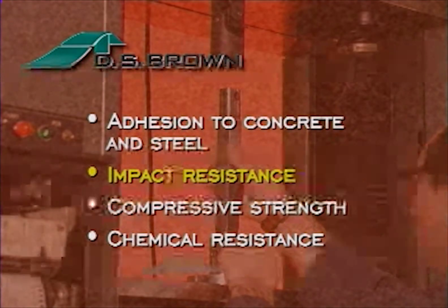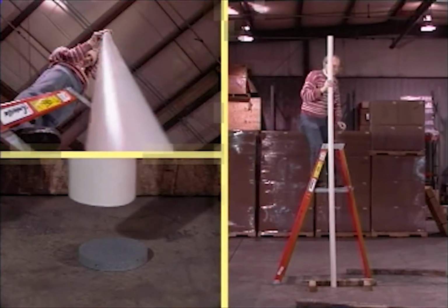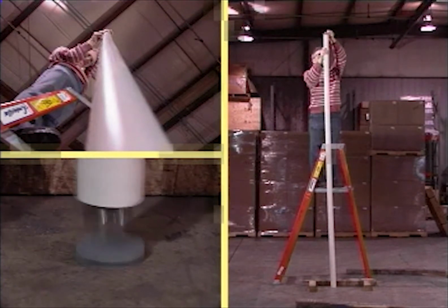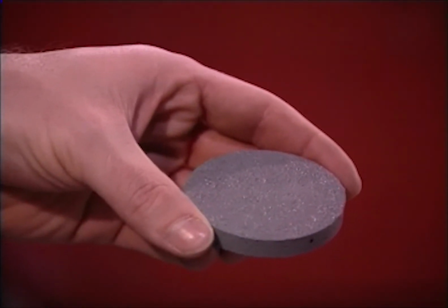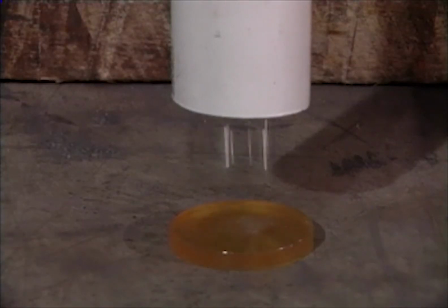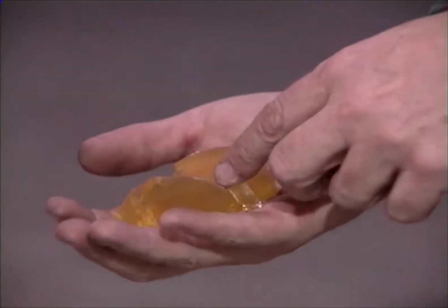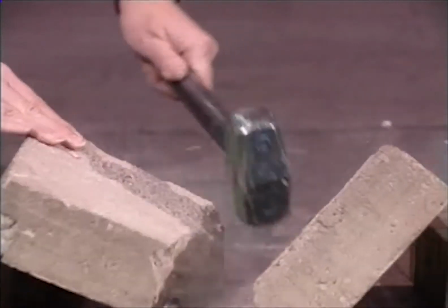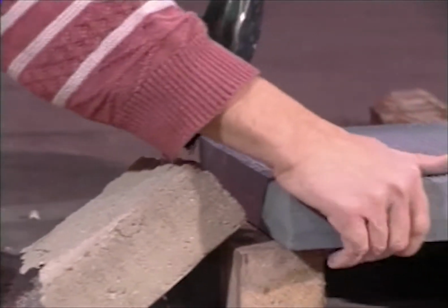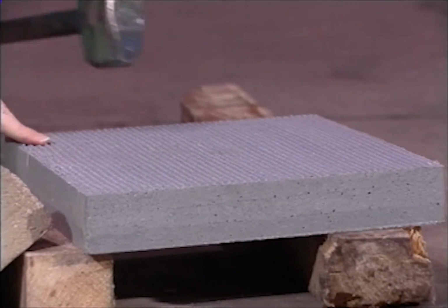In a specified impact test, a 1-pound steel ball is dropped from 10 feet onto a Delpatch disc chilled to minus 20 degrees Fahrenheit. The disc remains intact after impact. Epoxy-based materials frequently shatter under these conditions. Also, concrete shatters quite easily when hammered, while hammering has no effect on Delpatch.